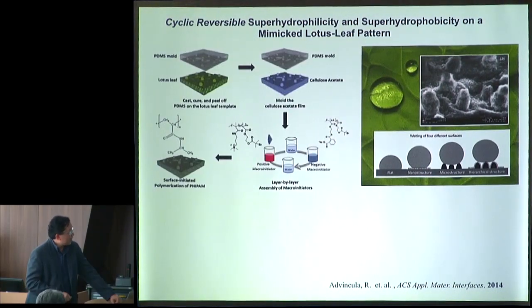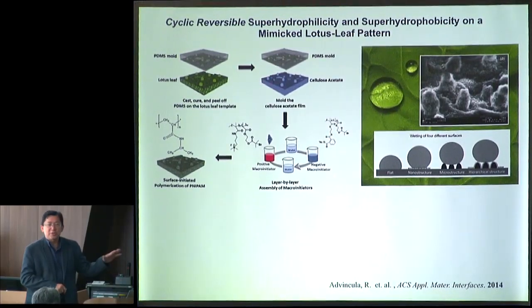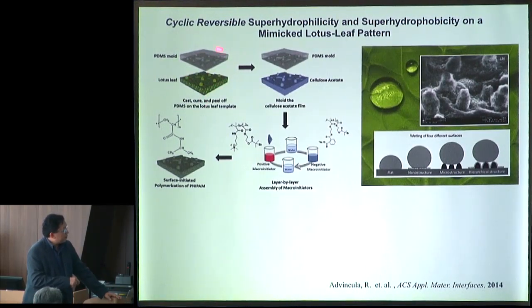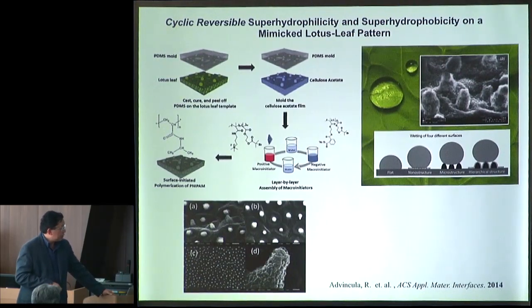So to do that, what we did is we copied the features of the Lotus Leaf using polydimethylsiloxane, a very common material used for stamping. Okay, so we copied the Lotus Leaf pattern on a PDMS mold, and then this PDMS mold we imprinted on a cellulose acetate film. We then did layer by layer of a polyelectrolyte macroinitiator for ATRP. And then we grew a well-known LCST polymer, poly-NIPAM, that of course has a transition of 32 degrees C. And then this is how the morphology looked like. So the original Lotus Leaf, the fake Lotus Leaf, and then after growing the polymer brushes, and you can see here some of the peninsular or corpuscle type of structures compared to the original.